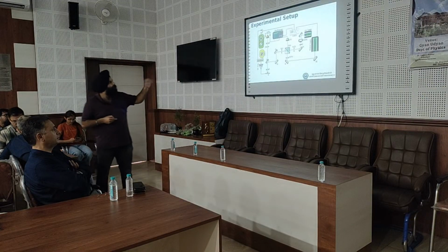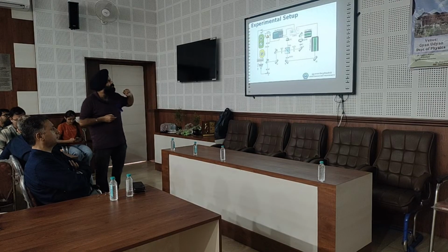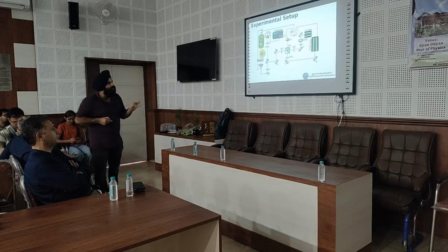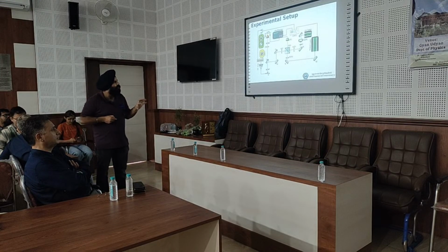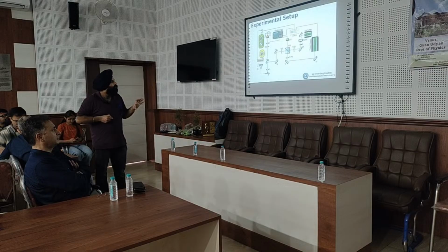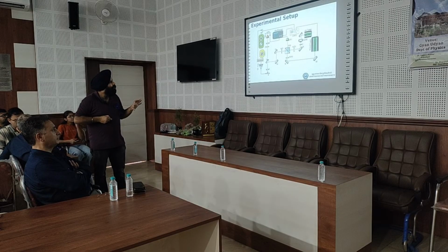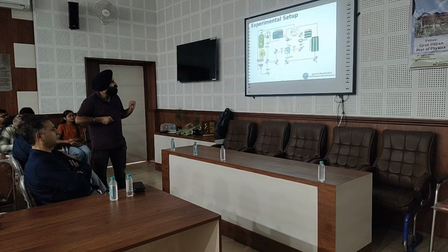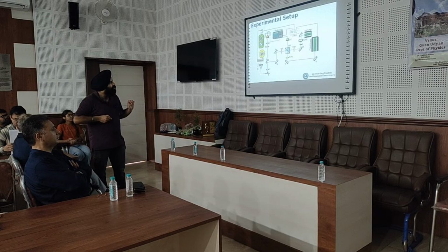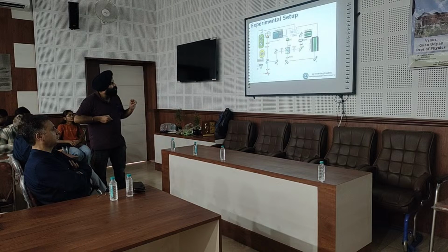And this is the setup that I made to study this and to do the quantum sensing. So this is a pulse laser, and then you have a CW laser, and we couple these two beams, and then we shine this onto a very special dichroic mirror which allows the 532 nanometer laser to reflect and lets the 600 nanometer or above light transmit. Okay, so using this mirror, we can shine the light on the sample, and then we collect the photoluminescence from the sample and record it in this APD.